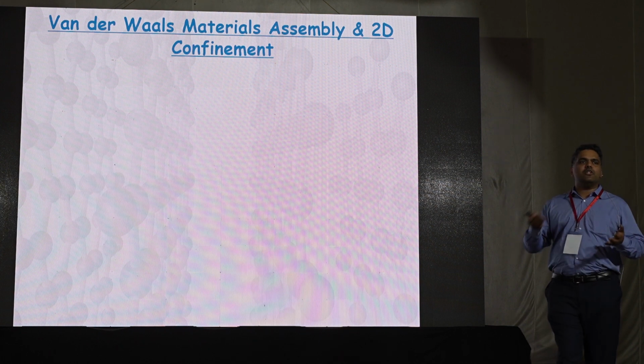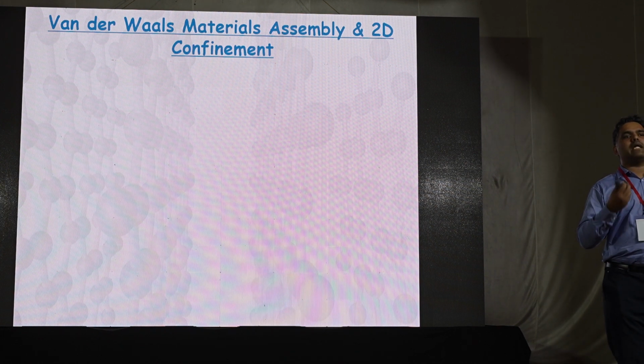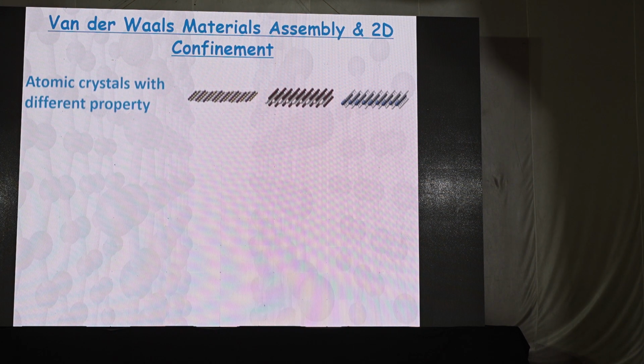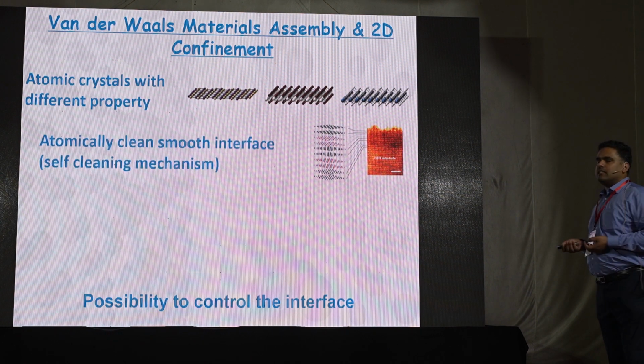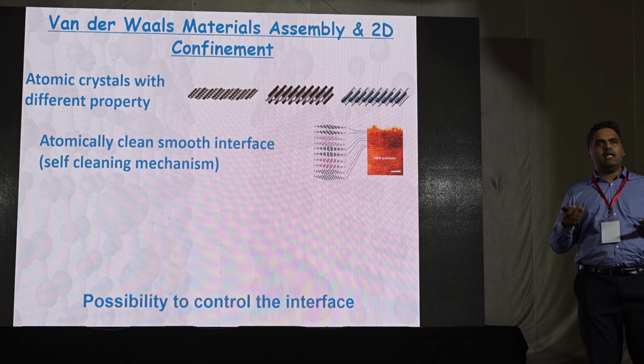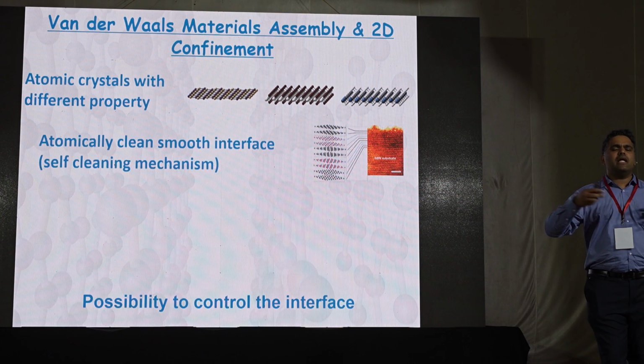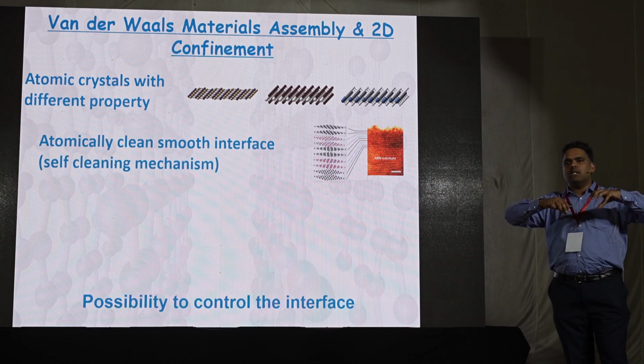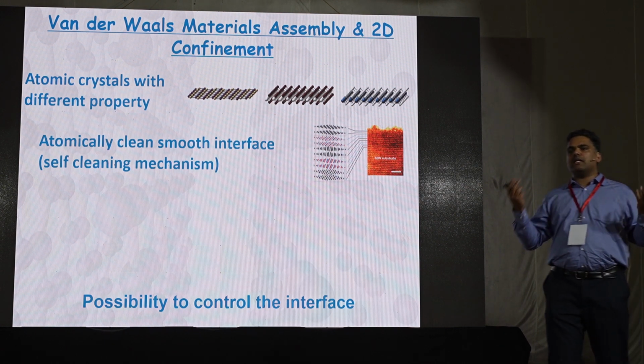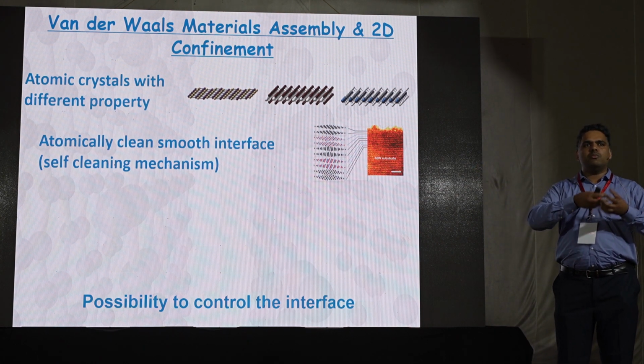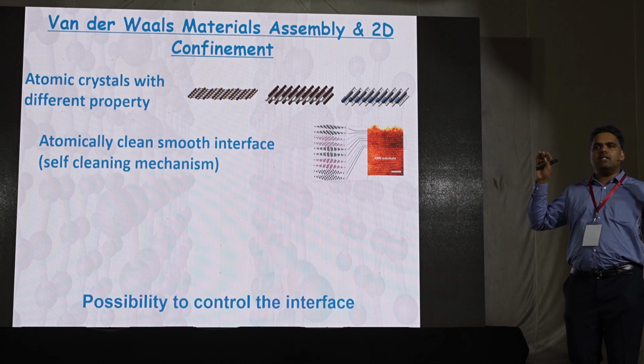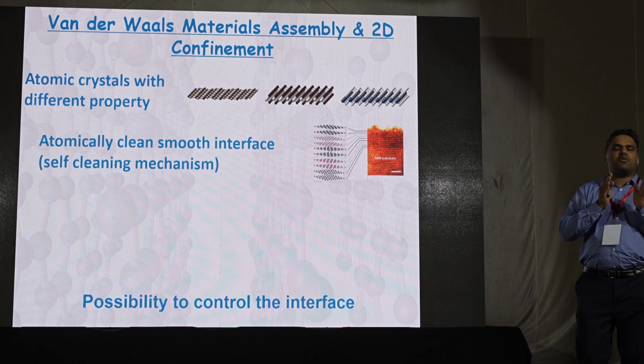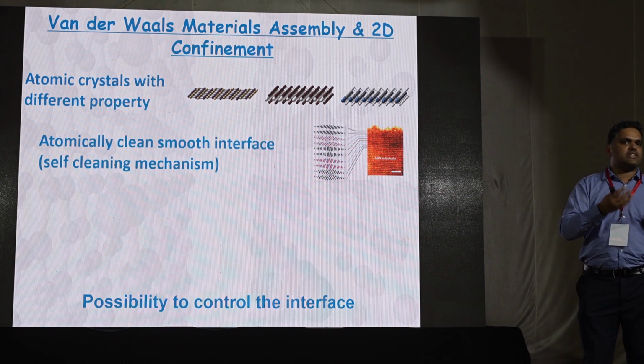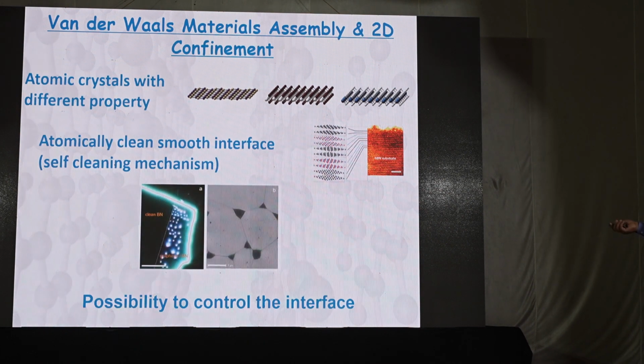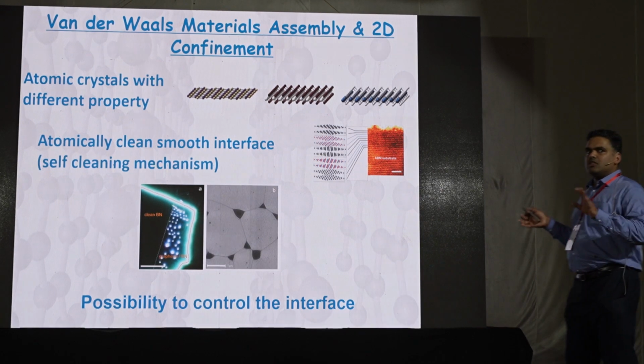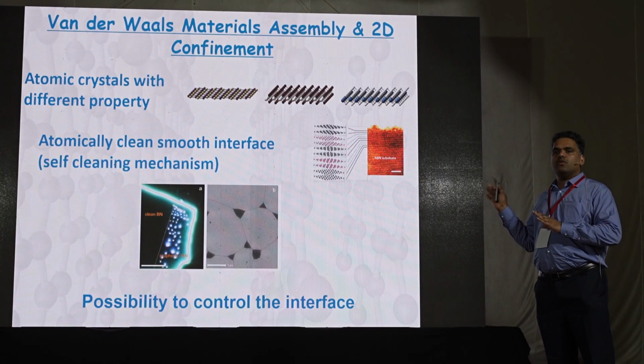as a chemist, maybe you can also use graphene for creating new materials or finding new chemistry between 2 layers, for example. Because we have many different materials, and these 2D materials are actually perfectly clean, atomically clean. You can imagine you take 2 layers and trap some molecules between these 2 layers, and they can do chemistry. In typical chemistry, you do chemical reactions in a test tube or in bulk. Exactly the same thing you can do between the atomic layers. Because this is in the nanometer or atomic regime, the science is different, confinement-induced reactions can be observed, etc. This is an example. Again, this cannot be done with all 2D materials, especially you can do this with hydrophobic material.